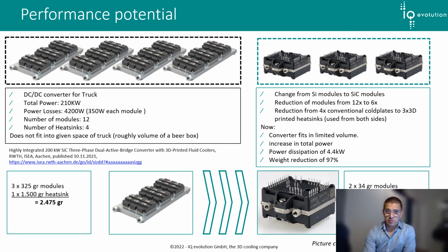Then they changed to IQ Evolution coolers, which enabled them to use smaller modules and fewer heatsinks, as well as switch to silicon carbide. These changes led to a reduction of 97% weight, an increase in power, and a fitting converter.